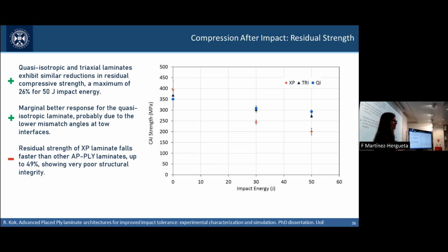So finally, just to end up, this is the last experiment, compression after impact. In compression after impact, we find two different trends. The triaxial and the quasi-isotropic laminates had a pretty good response when subjected to impact, losing up to a maximum of 26% of the residual strength capacity for a 50 joules impact energy.